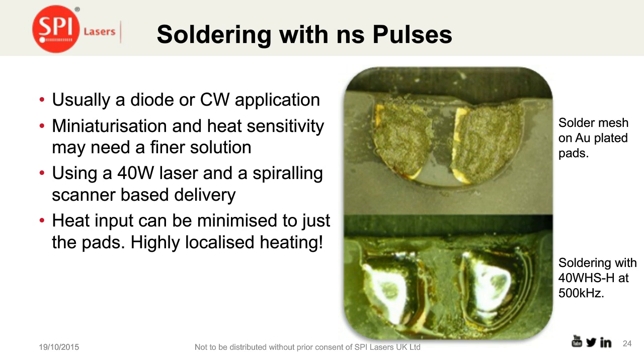And so we developed a process where we would spiral in the laser beam using long pulses, using a 40-watt laser with an M² of 3. In this case, the broader energy profile in the beam helped control the heat input, and we were able to just melt the solder balls on the pads themselves. You can see on the lower picture that solder balls that are still on the pad but weren't in the spiral are not even melted.